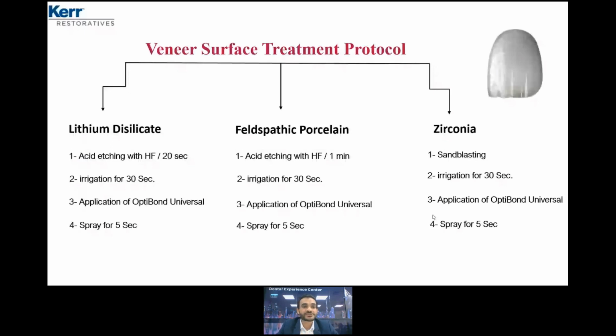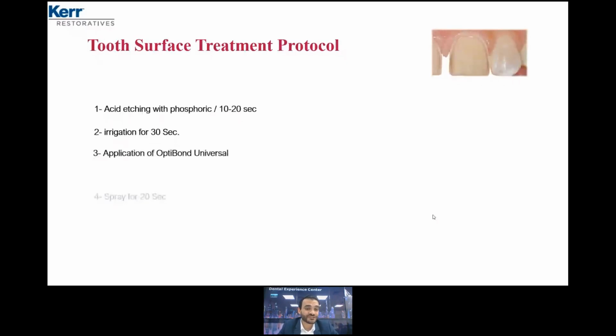Okay, the surface treatment protocol for the tooth, I believe it's clear for all of us. Acid etching for 10-20 seconds. Irrigation, application of OptiBond Universal, and spray for 20 seconds. And here I would like to say, because OptiBond Universal is a self-etch adhesive bonding agent, self-etch.